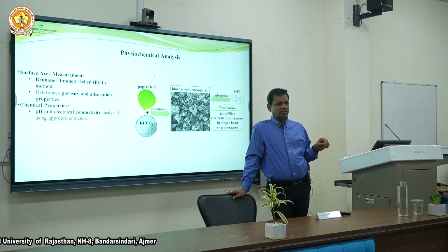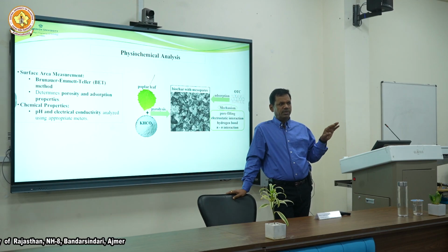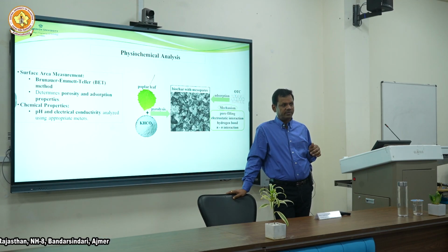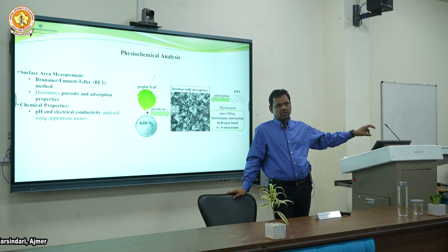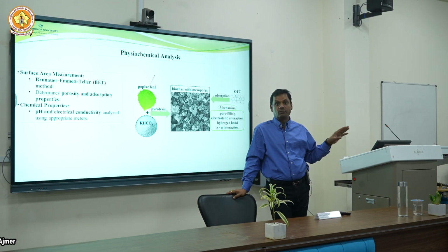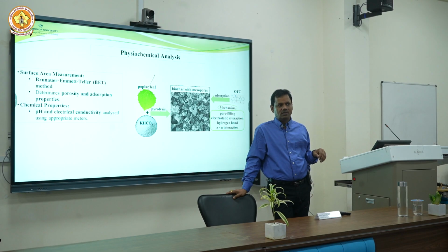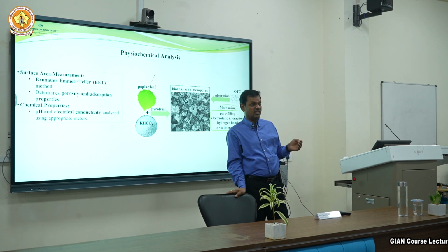In pyrolysis, we are going to 500, 600 temperature. pH is alkaline, because many ash components are left, carbon is there, more fixed carbon. So now you can match with the right soil quality, where which area has this soil quality, where we need pH high. If you are doing pyrolysis at a little lower temperature, pH is not high in biochar. More like closer to neutral or acidic.